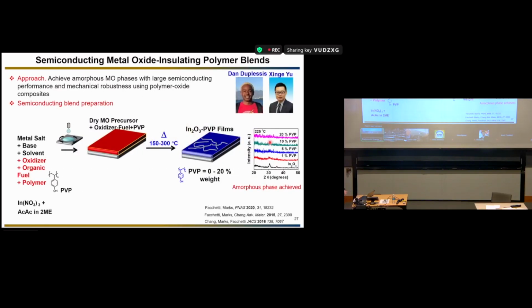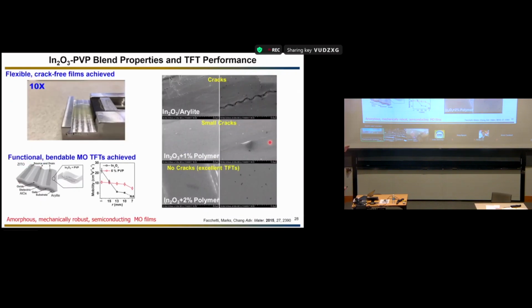And the way we did it is basically keeping the same formulation I just talked to you about before, and then we throw in a polymer inside. And then when you do the conversion chemistry, depending on the temperature, some of the polymer chain remain embedded in the oxide matrix. You can choose, depending on if you want more or less polymer, you can change the chemistry of the polymer, but the concept is you end up with a film which has some residue as memory of the polymer you are using. And having a polymer in there enhances the crystallization temperature. You get amorphous phases, also when using combustion. And also what you can do, you start making films which are more tolerable to deformation.